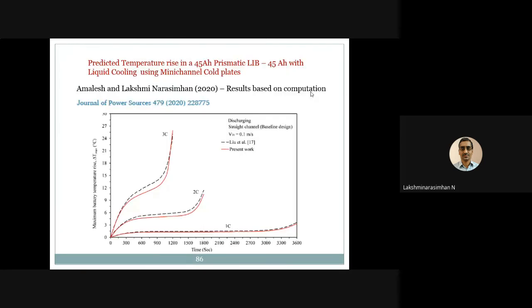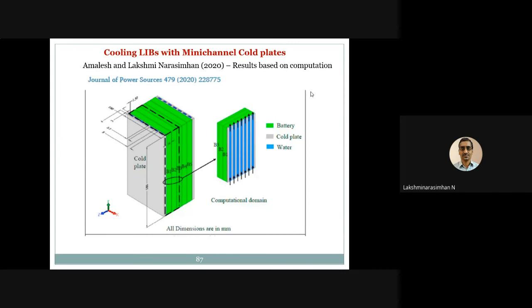And then we also studied mini channel cold plates. There also we found that the channels we have suggested recently have yielded a very good response in battery thermal management, and brought the temperatures of batteries down conveniently to 40 or 36 or less than that, even at 3C or 5C operations. So here is what we have proposed.